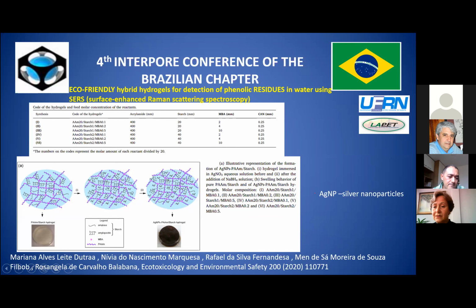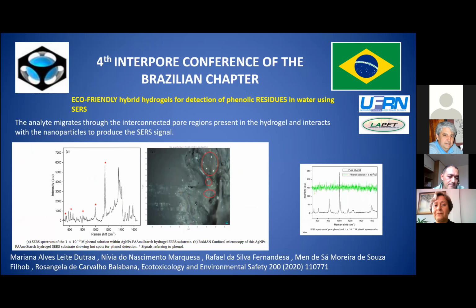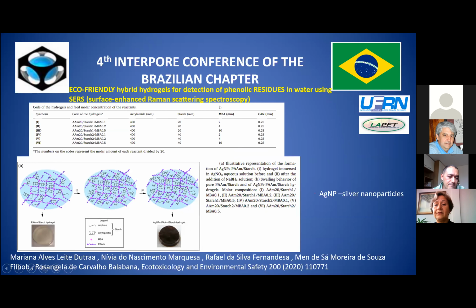And we saturated these hydrogels with silver nitrate. The silver nitrate was reduced, in this case the cation of silver was reduced to silver nanoparticles inside the hydrogels. So here we have black hydrogels due to the presence of silver nanoparticles. And this system, the hydrogel with silver nanoparticles, was applied in a technique named SERS, that means surface enhanced Raman scattering spectroscopy.